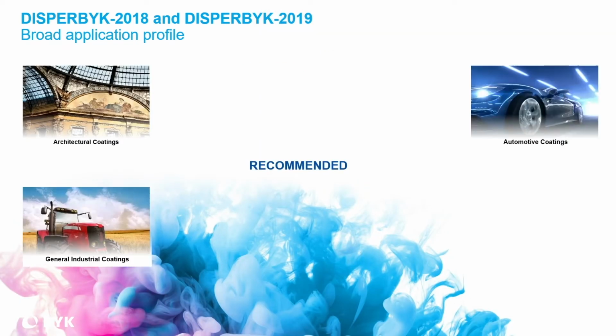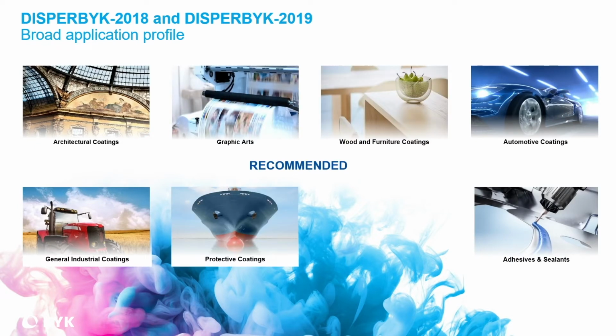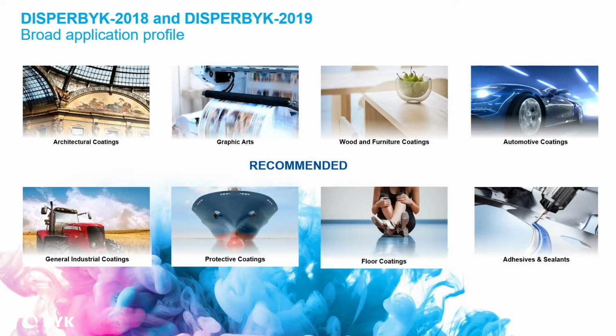And you see it here. We tested it in all of our end users. And we achieved always good results in architectural coatings, in water-based binder-free pigment concentrates, as well as in silicate paints. It is very stable also at high pH values. We achieved excellent results in graphic art applications. In wood and furniture coatings, excellent transparency, which is very important. You want to see the nice structure of the wood. So for organic pigments and transparent iron oxides, excellent solution.